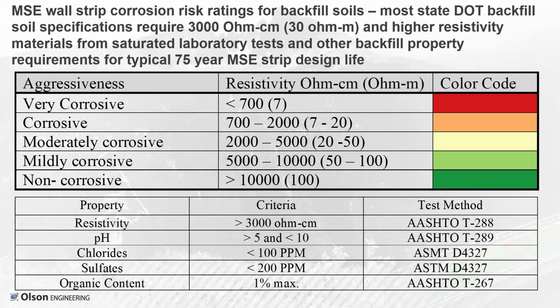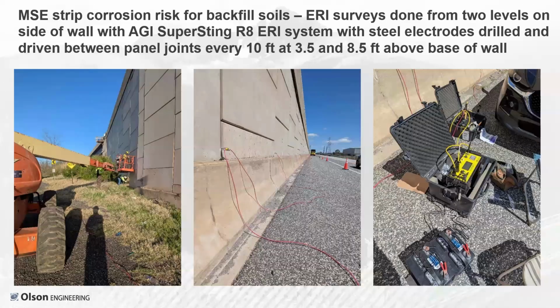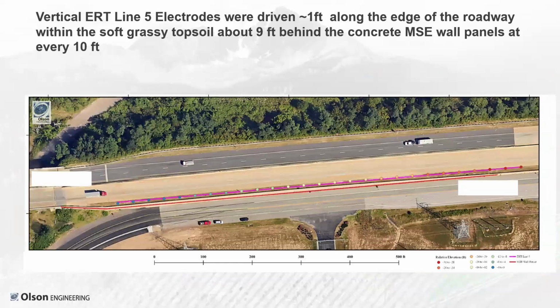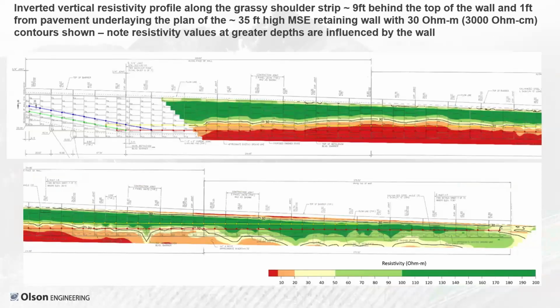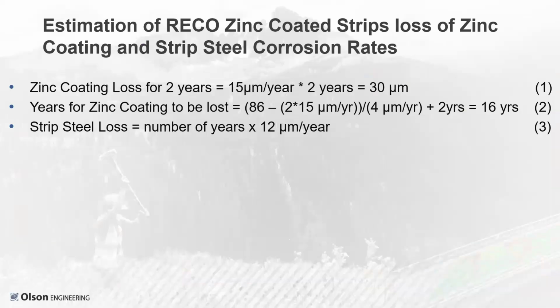And so when you drop from the 3,000 ohm centimeters or 30 ohm meters, as we reported it, below that is when you get to moderately corrosive to very corrosive. And we found some areas with that. So with that as a bit of a preface to what I'm going to talk about, we took this information, and this was a reinforced earth company wall, and they did have the design drawings and records, if you will, for the wall, which is very helpful.